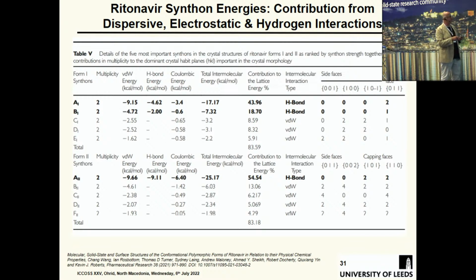And here I just want to show you how this pans out from the synthons of the 2 forms to the extrinsic synthons. So now we look at those synthons and we then cut them with a habit plane and see which ones have been cut. And the important things you see here are these important hydrogen bond synthons. See all these rows of zeros? I won't go into it too much. See these rows of zeros? They only contribute to the capping faces of the crystal.